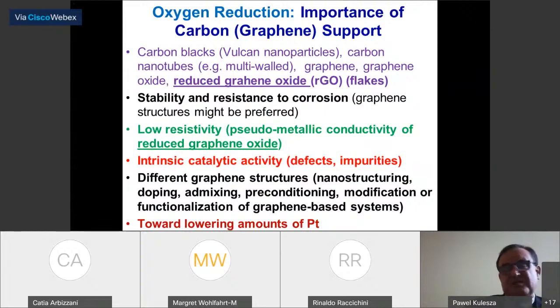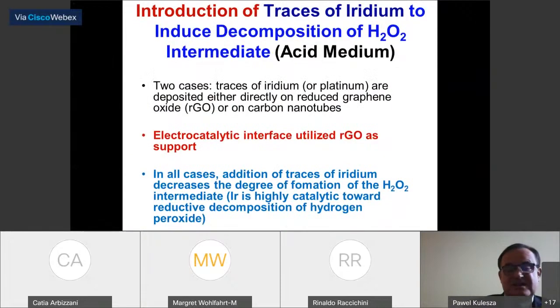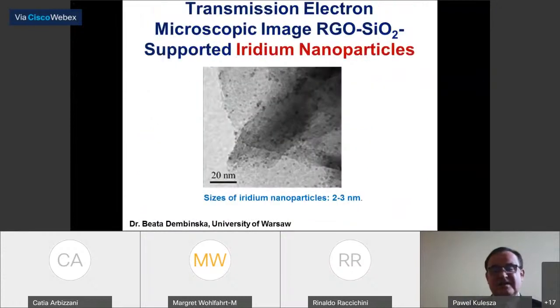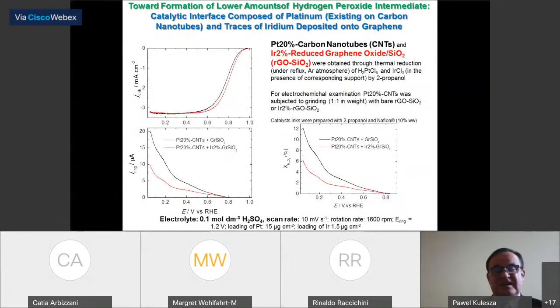So we are looking for different combinations of the systems. There's a lot of work done in this area, but I would like to mention only one part, about adding traces of iridium. It goes back a little bit to the concept discussed with Roberto that we need to do something with hydrogen peroxide. Iridium is a very good catalyst for the decomposition of hydrogen peroxide, much better than as a catalyst for the oxygen reduction. We can put traces, a small amount of iridium, as you see, very small particles, and indeed you shift potential and you decrease formation of hydrogen peroxide.